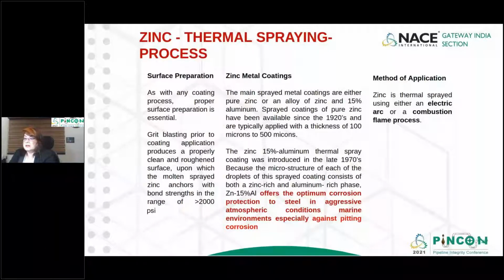Because the microstructure of each of the droplets of the sprayed coating consists of both zinc-rich and aluminum-rich phases, zinc and 15% aluminum provide the optimum corrosion protection to steel in aggressive atmospheric conditions like marine environments, especially against pitting corrosion. There are two types of zinc thermal spray coating application: by electric arc or a combustion flame process.